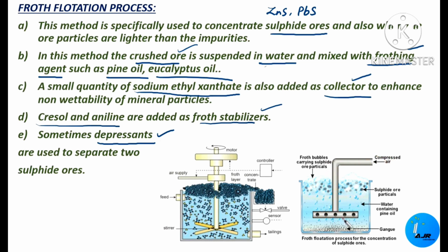We are adding the mineral particles with water and the frothing agents like pine oil and eucalyptus oil, and also sodium ethyl xanthate, that is the collector, is added, and the froth stabilizers like cresol and aniline are also added. So that will be present here. The water containing pine oil and the sulfide ore particles, everything will be here.